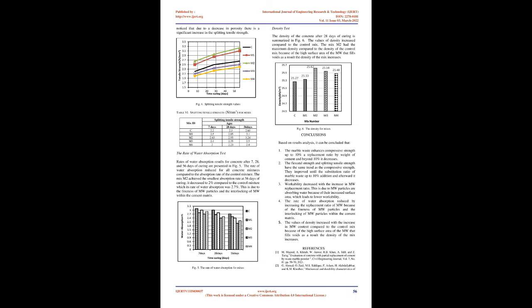It was 10.4%, 9.03%, and 9.4% higher compared to the compressive strength of the control mix at 7, 28, and 56 days curing periods, respectively. The increased compressive strength was due to the pore filling achieved by MW because of the increased fineness of MW particles, which leads to an increase in the density of the concrete mixture. MW particles have higher absorption of water, which leads to a decrease in the ratio of water to cement and thus increases the compressive strength. Further replacement of cement beyond 10% with MW resulted in decreased compressive strength. This is due to reduced binder content and dilution of available cement content.